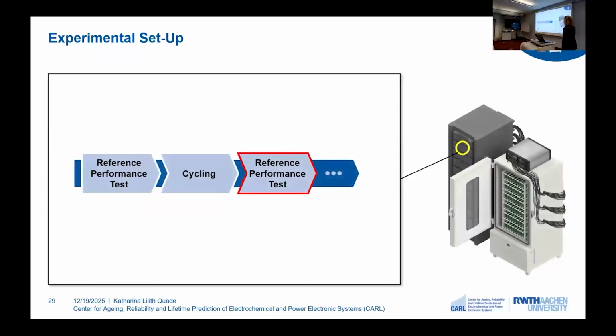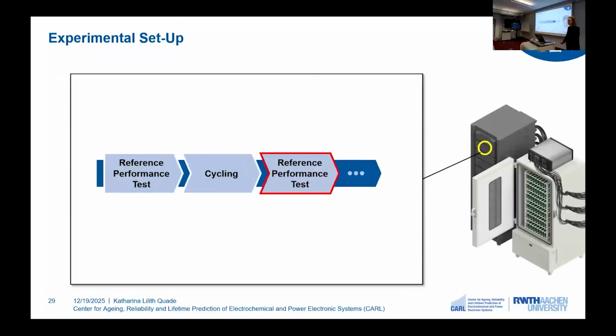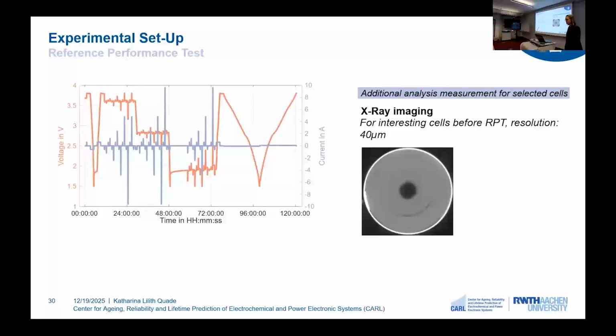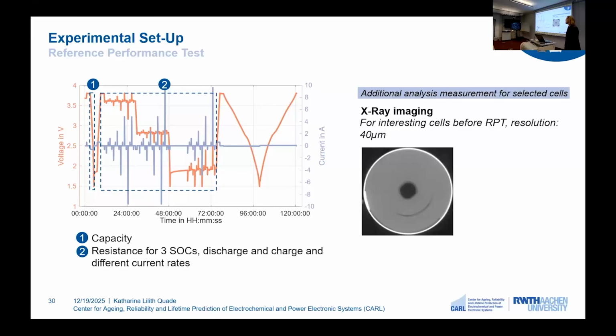So let's have a look at the reference performance test where we want to assess the state of our battery. Here on the left-hand side, you can see the general procedure, the voltage in orange, and the current in purple. And of course, an important aging indicator is the capacity. So first, we fully discharge our cell to measure the capacity. Then we do pulse measurements to analyze the resistance for 3 different SOC levels or voltage levels in discharge and charge direction, and also for different current rates.